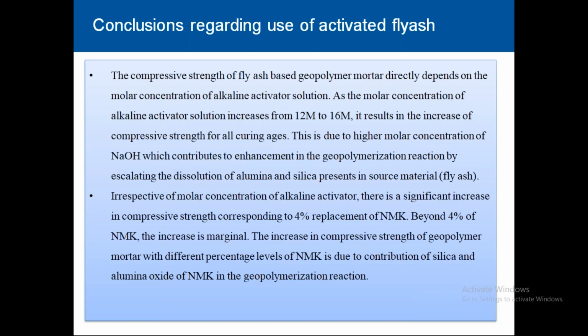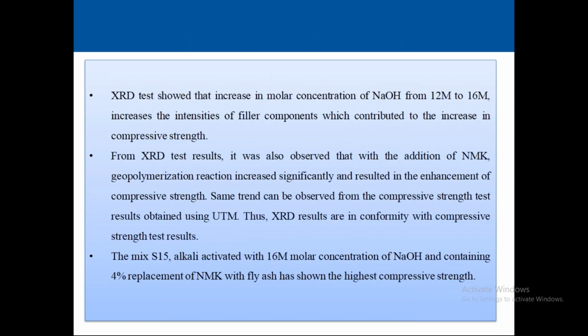So second is, irrespective of the molar concentration of alkaline activator, there is a significant increase in compressive strength corresponding to 4% replacement of NMK. We found that beyond 4%, the increase is marginal. The increase in compressive strength with different percentages is due to contribution of silica and aluminum oxide in the geopolymerization reaction. XRD test results showed that increase in molar concentration of NaOH from 12 M to 16 M increases the intensities of filler components, which contributed to the increase in compressive strength.